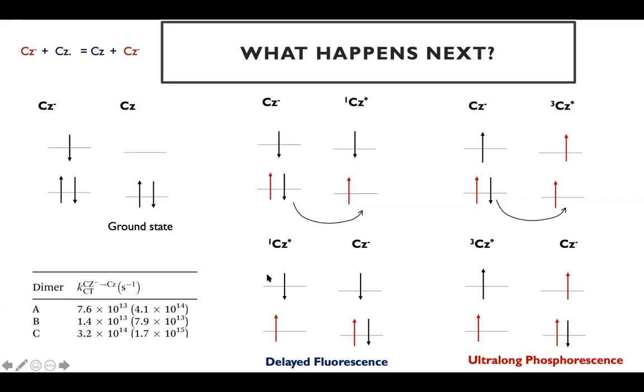This mechanism will help you justify delayed fluorescence, which is also found in carbazole. It is less important than ultralong phosphorescence, because of the lifetimes of the singlet states, but it also happens and is being detected experimentally. And you can also justify why the excited states of carbazole are ultralong. I mean, why they stay for a long time. Essentially, every time a negatively charged carbazole finds an excited state, you can have this electron transfer process that can in a way enhance the lifetime of the excited state.